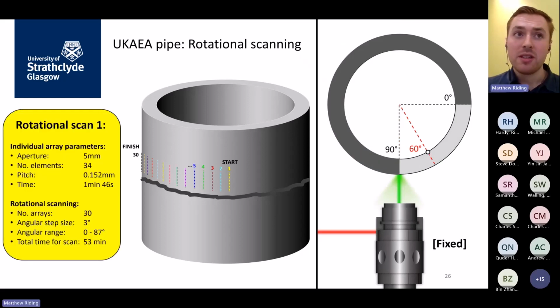There are the scan parameters, a much smaller aperture for this one, and each individual capture was quite quick, just less than 2 minutes, but the overall scan time for completing this 90-degree sector was almost 1 hour. So again, speed is a real drawback at this stage, but it's not been optimized for speed, so that's the priority of our future work.